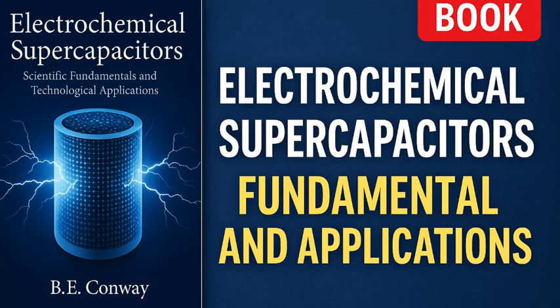Activated carbons commonly have around 500 to 2000 square meters of internal surface area per gram. All that microscopic surface in the form of pores and fissures is where double layer charge accumulates. As noted, high surface area is directly proportional to capacitance. Specific capacitances for activated carbon range from 100 to around 300 farads per gram, depending on the material and electrolyte. A typical value is of the order of 150 farads per gram in aqueous electrolytes and about 100 farads per gram or slightly lower in organic electrolyte.